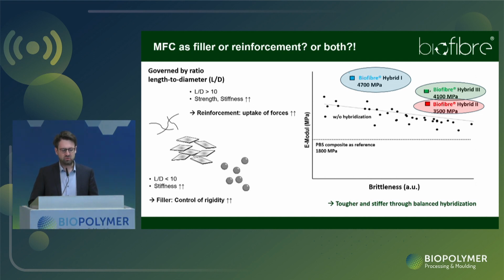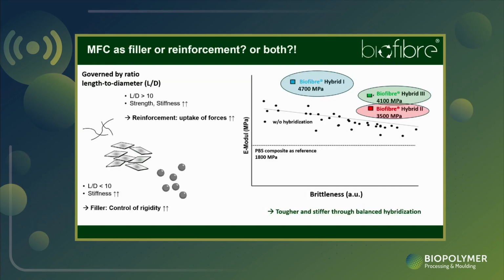And in contrast to that, you talk about a filler-like behavior when you talk about the length to diameter ratio less than 10. This is, let's say, an empirical equation, and it's a definition in how to divide those two geometries. And what we saw is that when you combine those two different geometries, you can enhance the mechanical properties in terms of brittleness or toughness over the E modulus.